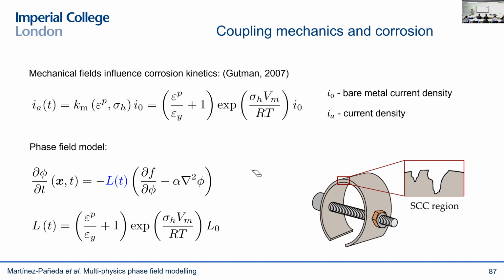So we can incorporate them into our model because our phase field mobility coefficient, which was before a constant, can be quantitatively related to the corrosion current density. So we can define this phase field mobility coefficient as a function of those mechanical fields. And then we can benchmark our predictions comparing with those experiments on the C-ring test, where we can measure for different levels of applied load the propagation of corrosion defects.